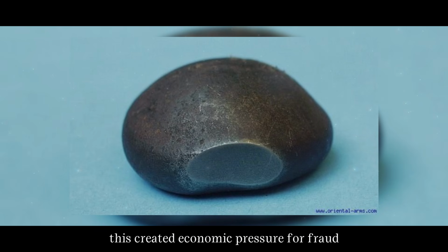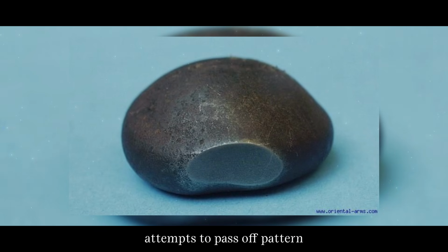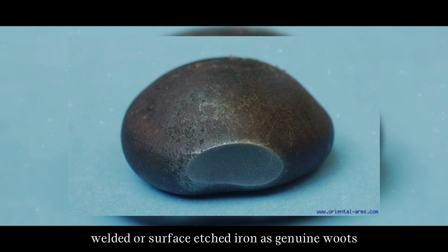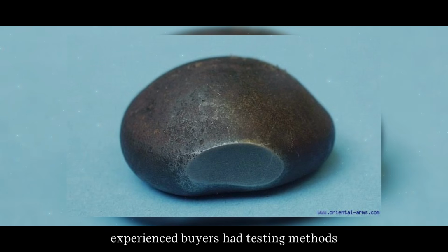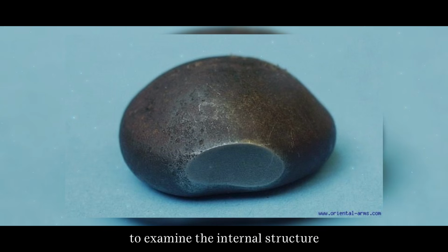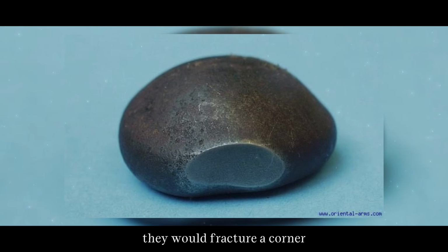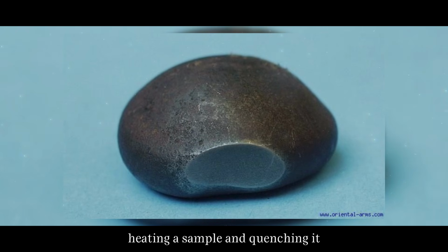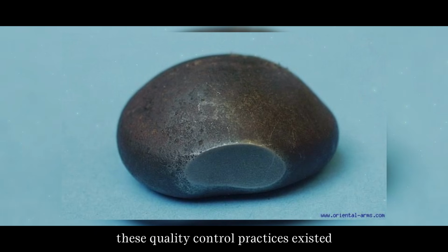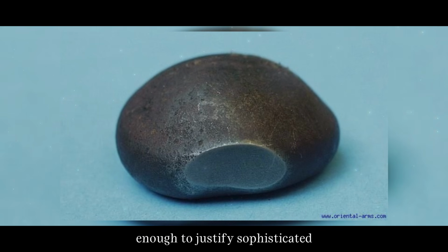This created economic pressure for fraud. Attempts to pass off pattern-welded or surface-etched iron as genuine wootz. Experienced buyers had testing methods. They would file a small section of the ingot to examine the internal structure. They would fracture a corner to inspect the grain pattern at the break. Some sources mention heating a sample and quenching it to verify the hardening response. These quality control practices existed because the material was valuable enough to justify sophisticated authentication procedures.